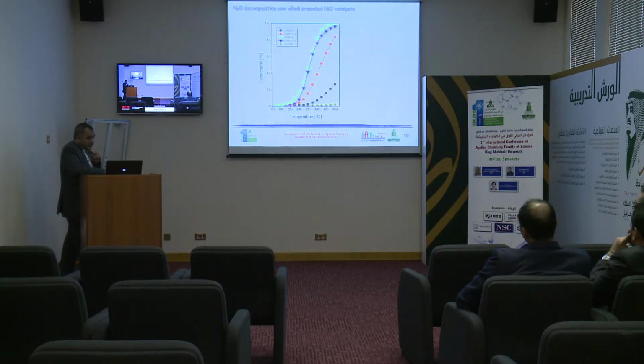Going to the activity data, nitrous oxide decomposition over nickel oxide or bare nickel oxide is really a poor catalyst. It's showing conversion less than 5% at 500 degrees. Doping this catalyst with lithium for sure increases the activity slightly. Going to sodium, activity increases markedly, and potassium and cesium show the most active catalysts. So we have now to try to understand what's the reason for this higher activity of cesium and potassium.